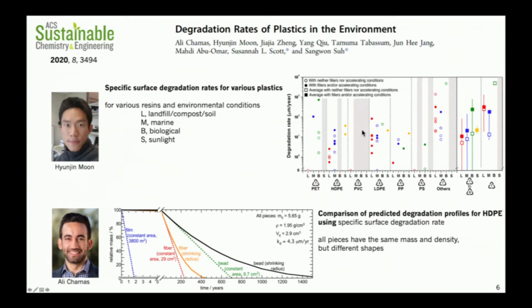And if you analyze all the papers where there is enough information to actually say something about degradation rates in the environment across the different types of commodity polymers that we know, we see that there are many orders of magnitude variation, even when you start to separate the studies into the different environmental compartments where the degradation is happening. There are huge uncertainties, and these error bars on the far right represent that, huge error bars in what we know about these materials. And we think that part of this comes from the fact that the degradation in the environment is actually a surface process. It's a surface limited process.